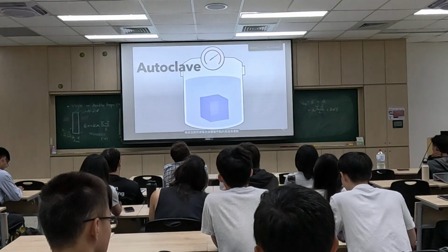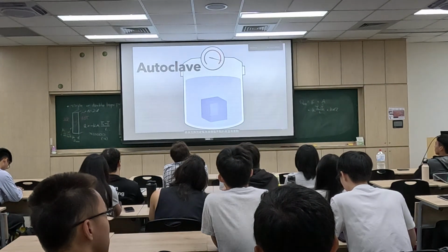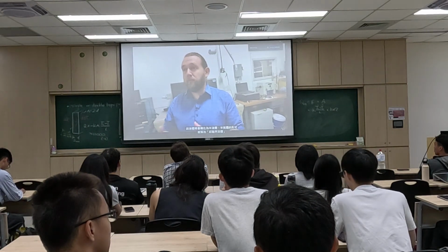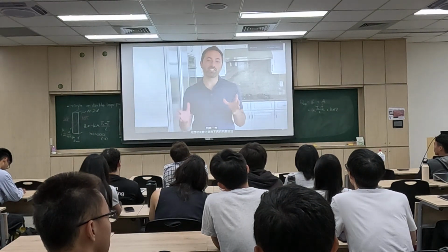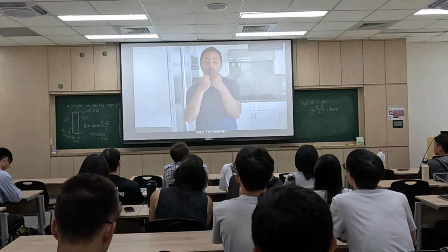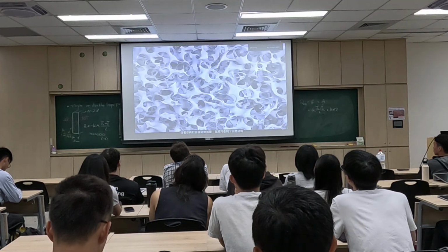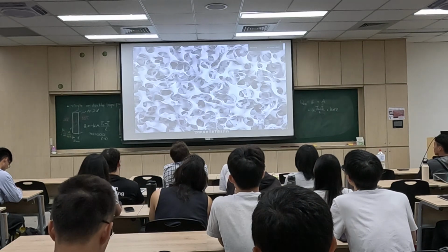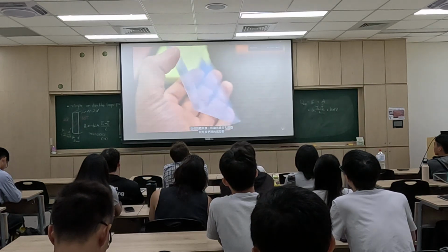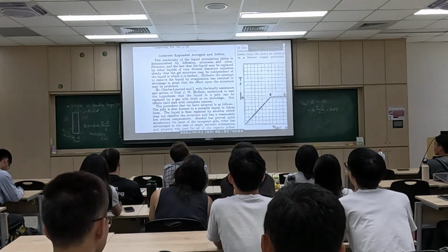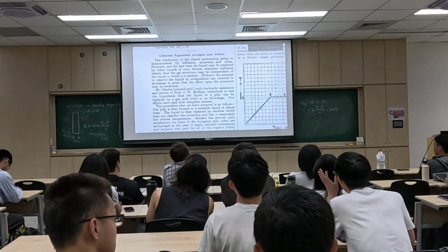By heating it to the high temperature point called the critical point of the liquid, that liquid transforms into a semi-liquid, semi-gas called supercritical fluid. At this point, there is no longer a distinction between liquid and gas. Those molecules are no longer pulling on each other. So once you depressurize the vessel, that solid skeleton, that 1% of the mass of the gel, is left behind intact, except where there was liquid in the pores before is now gas. And that solid skeleton, that nanopore solid, is what we call aerogel. Kistler published his findings in Nature in 1931.